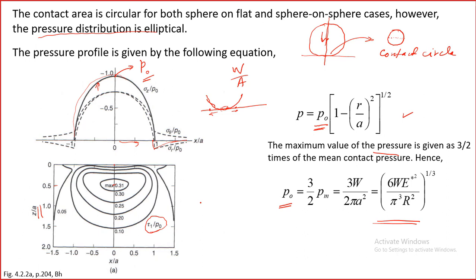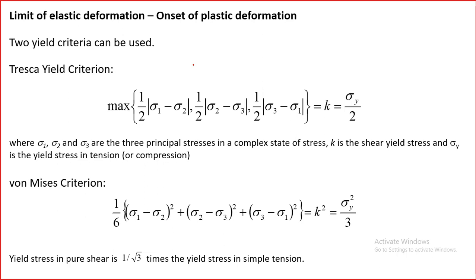So these are quite well established analyses, and we can learn from here about the contact pressure, the actual contact stress in a tribological contact, and we can understand about these shear stresses in the subsurface. As the load is increased, the elastic deformation will continue, but at some point the onset of plastic deformation will begin. The plastic deformation will start because the stress has exceeded the material's yield strength.